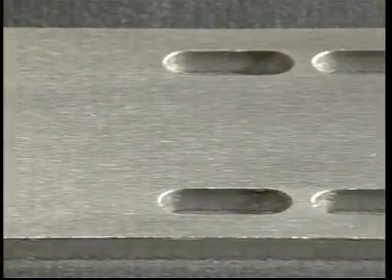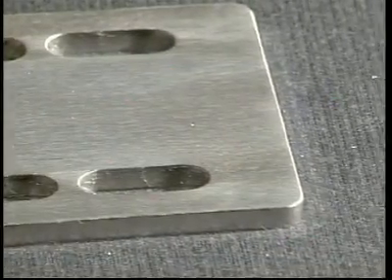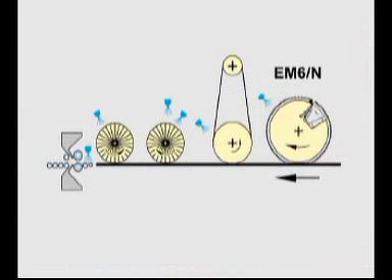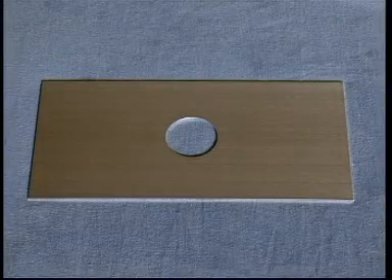Graining. Graining is a surface grinding process and requires an even and high grinding pressure over the entire surface. The most suitable working element for this process is a wide belt unit with a small diameter contact drum with a hard, inflexible rubber backing for an even surface finish. Graining should always be performed after deburring. ERNST finishing systems can achieve homogeneous, consistent, qualified surfaces such as a number 3 or number 4 stainless steel finish. The grain typically is refined by applying stainless steel or Scotch-Brite brushing after the graining process.